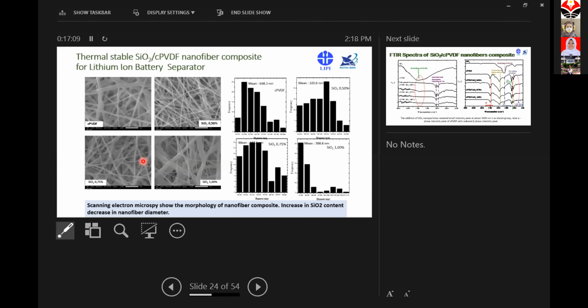So we try to make a nanofiber composite with different amounts of silica. You can see here we try to increase the concentration of silica in the nanofiber from 0.5% to 1%. You can see here, when the silica content in the nanofiber increases, the nanofiber diameter decreases.